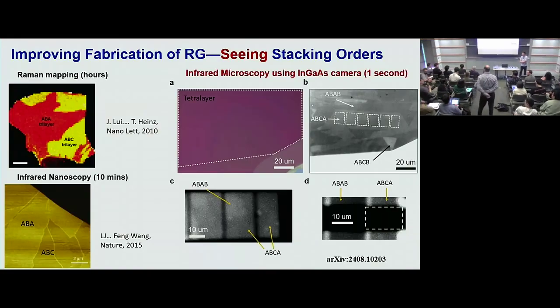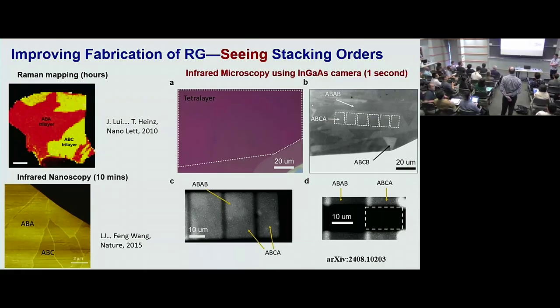Have you applied in-plane field to check these Pauli violations? Short answer is we don't have a vector magnet. So it hasn't been checked yet. But maybe it's not terribly difficult to do because out-of-plane critical field is already 1 Tesla. If you have a small misalignment, maybe fine. Yeah, and also how that in-plane magnetic field will change the phase boundaries around. I think that's also very interesting information. I agree.